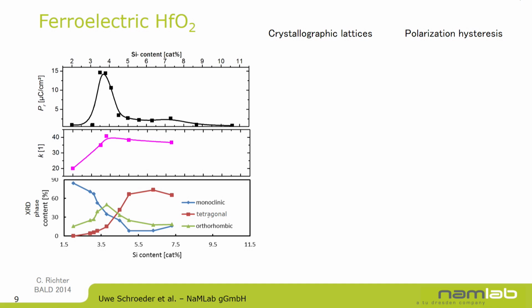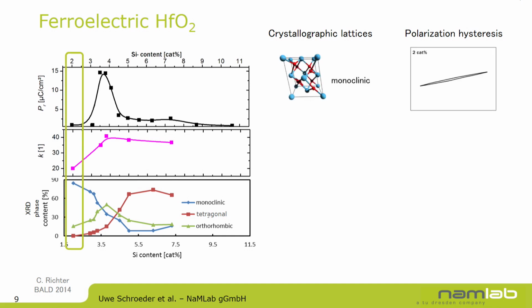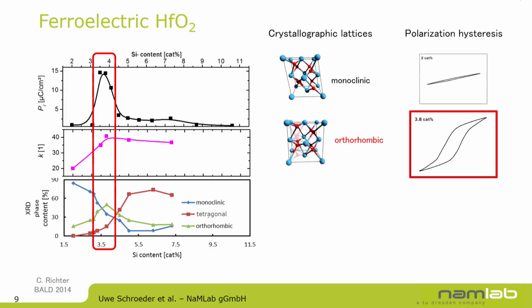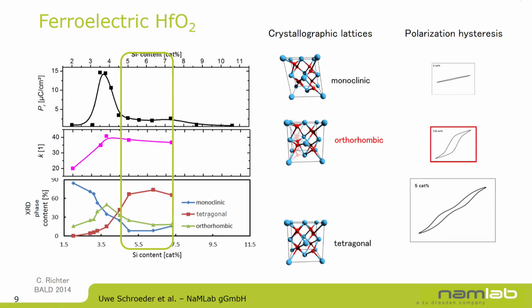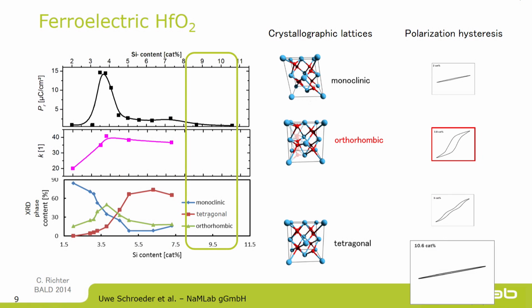Okay, let's have a closer look into this. Here's remnant polarization, the dielectric constant, and the phase content as looked into by Rietveld refinement of the XRD pattern. And here's the pure hafnium oxide, the monoclinic phase, and as mentioned, no hysteresis loop. Then if you increase the silicon content in hafnium oxide, you had this nice hysteresis shape for the orthorhombic phase of the material. And then in between the orthorhombic and the tetragonal phase, this pinched hysteresis loop, which looked like antiferroelectric, and we're still in discussion about what we really can see here. And then once you are completely tetragonal, all the properties disappear again.